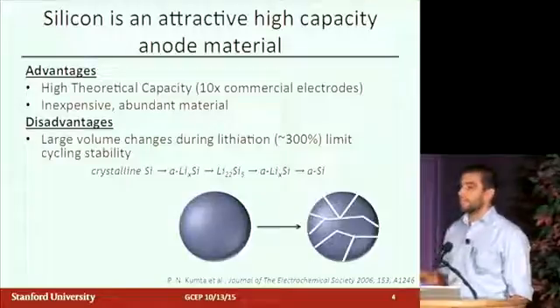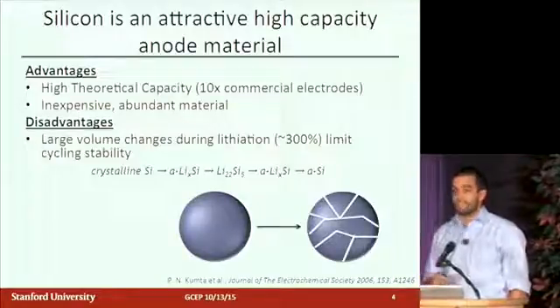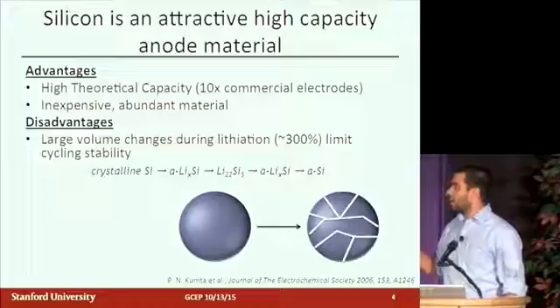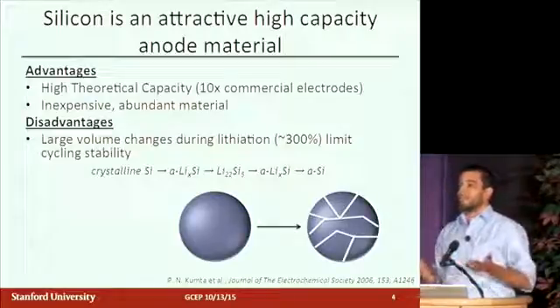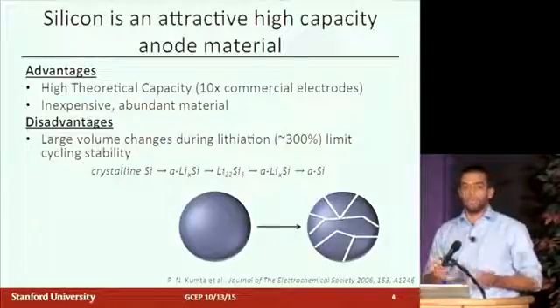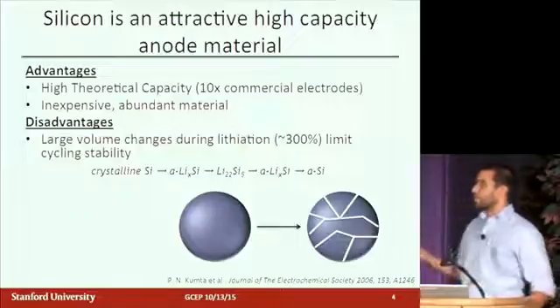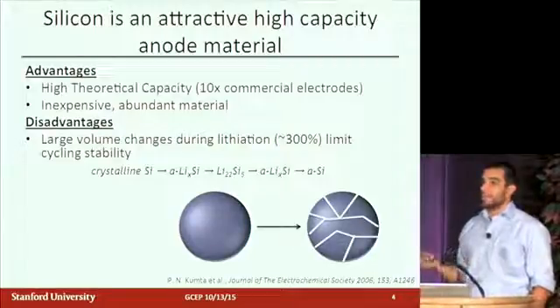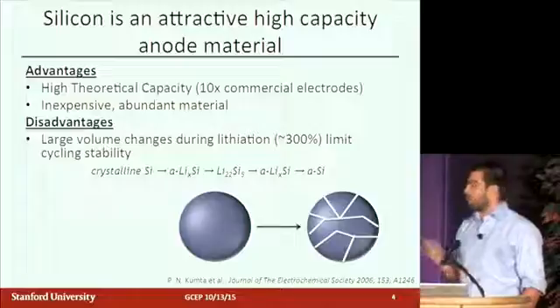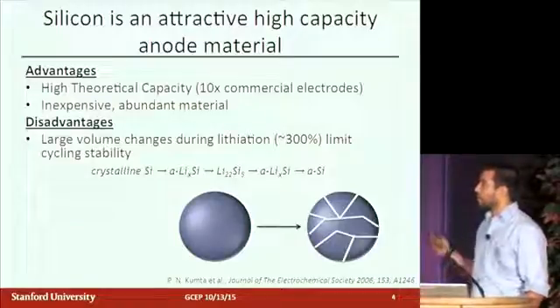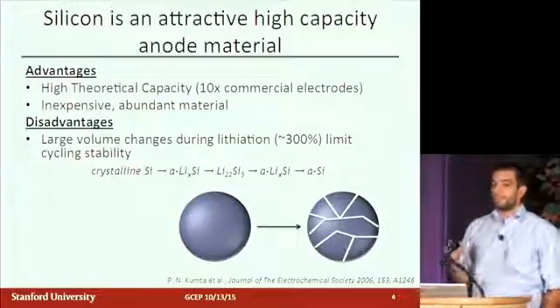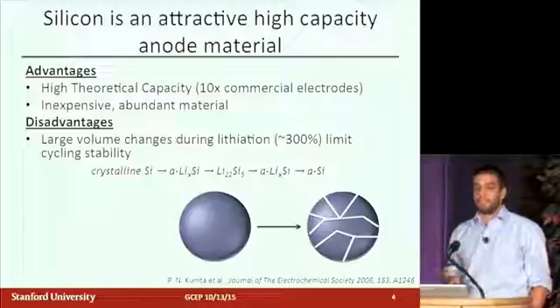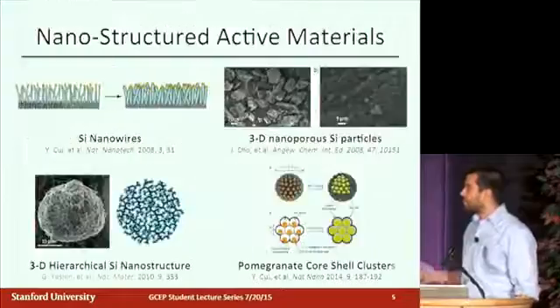And so what instead happens is you have fracture and pulverization of your electrodes, and that leads to cracking. You'll either have pieces of your electrode mechanically delaminate, or you'll have new surface area that forms, and there's an electrolyte decomposition reaction that happens due to the really low potential of these silicon electrodes. Those are the two problems that people are aiming to solve to make these cells have more cycle life, which is what we want.